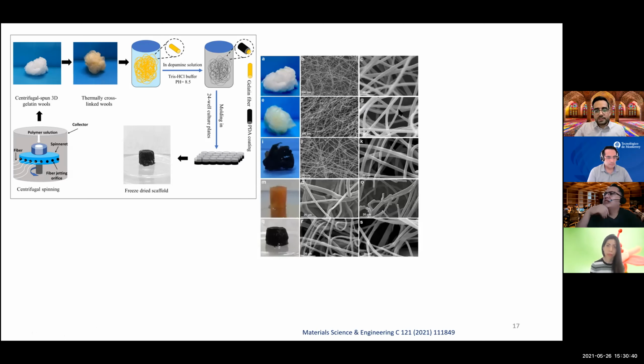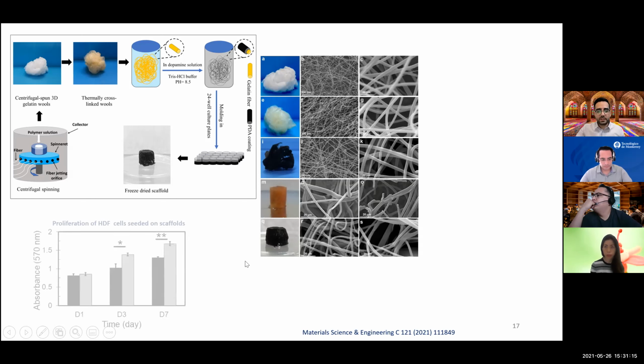And you can see the scanning electron microscopy, SEM micrographs of different scaffolds. This one is the pure gelatin, the other one is the cross-linked. This one contains a layer of polydopamine. This one is after molding and after freeze drying, and this one is the sample containing polydopamine. And as you can see here, all samples have a long and continuous fibrous structure, and it means that during the preparation of the scaffolds, we don't have any significant changes regarding the structure.